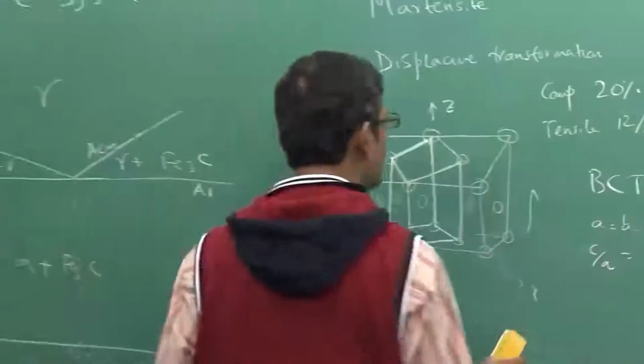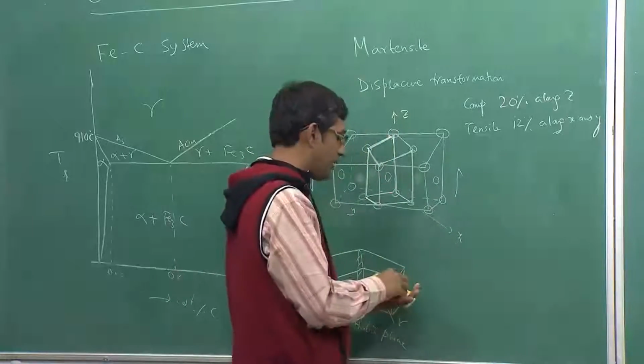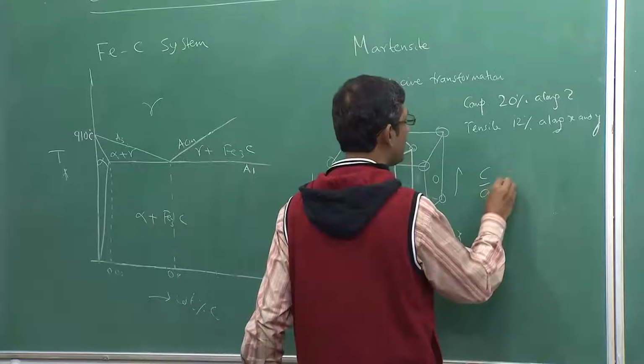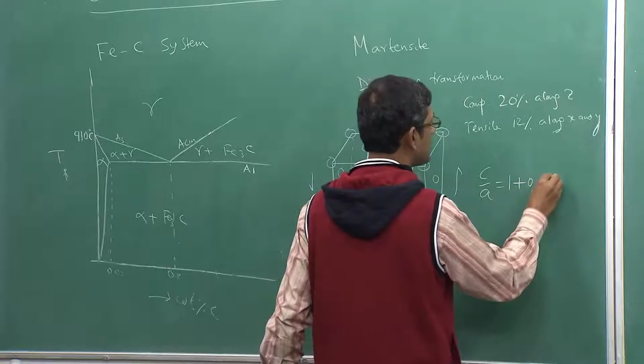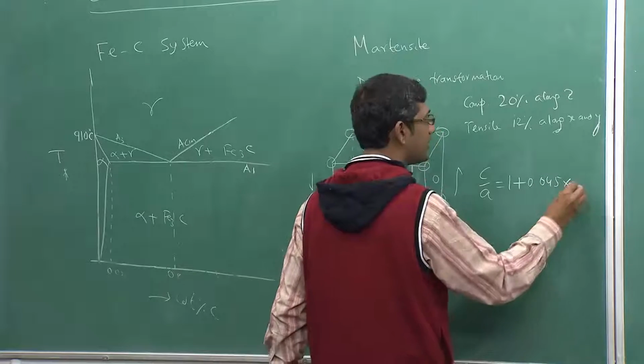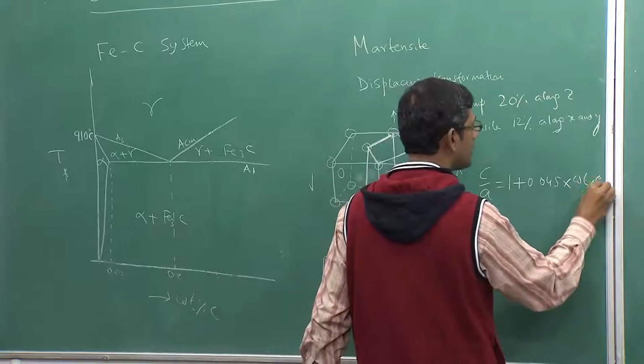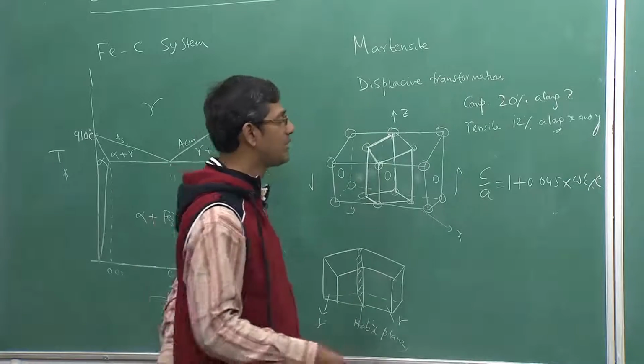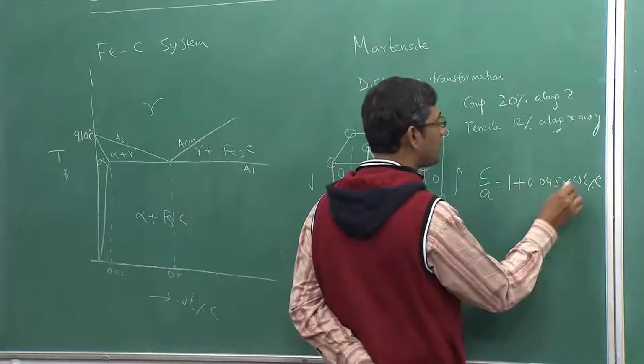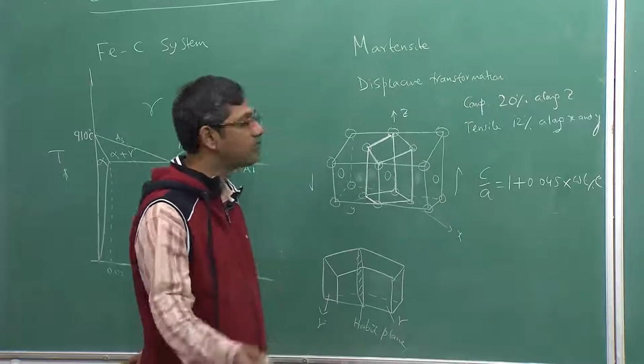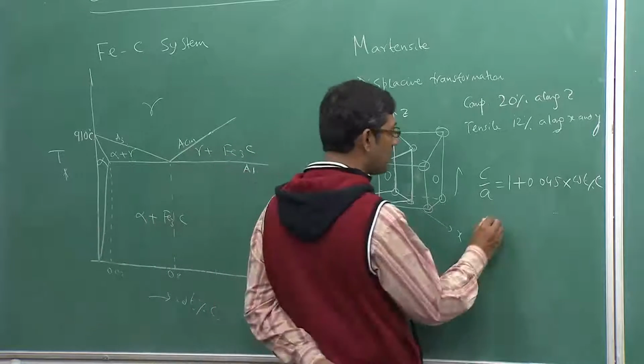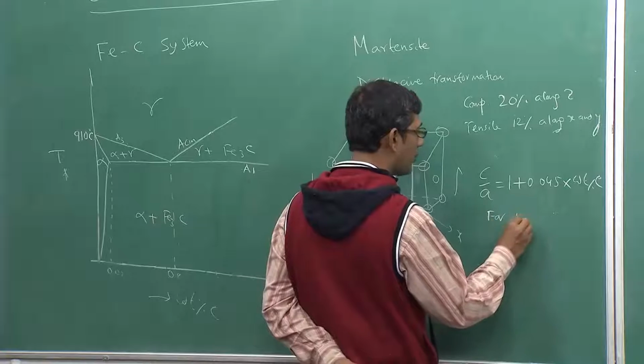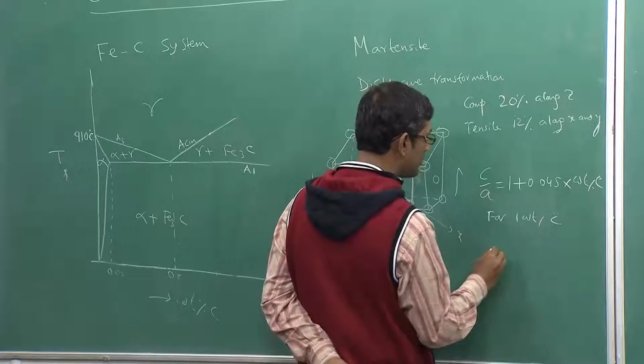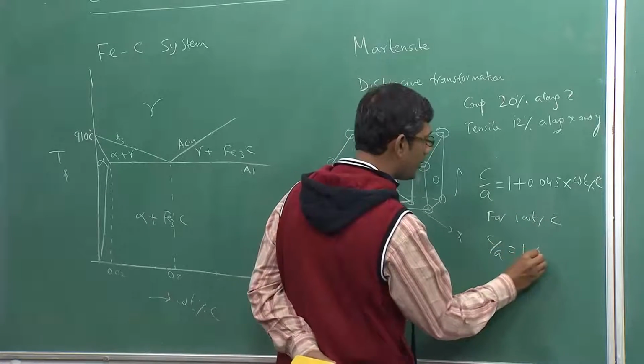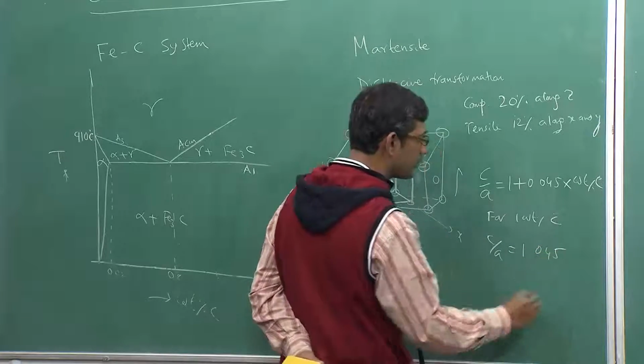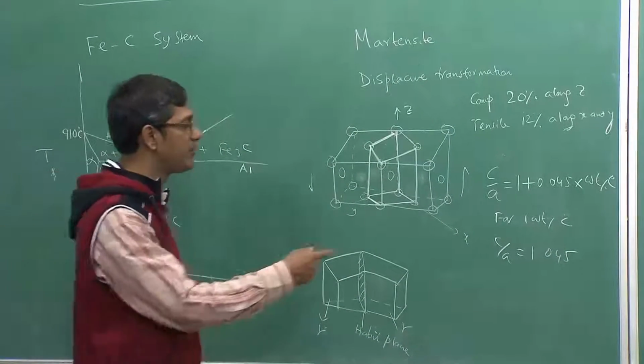Well, a few important aspects before I finish this lecture, we are going to discuss more on martensite in the next lecture also. One is that the C by A ratio, which I told you, basically depends on the carbon percentage in steel. So, C by A is basically 1 plus 0.045 into the weight percent of carbon in steel. Suppose you have 1 weight percent carbon steel, for 1 weight percent carbon steel, the C by A is 1.045. That is, there is very small difference between the C and A axes.